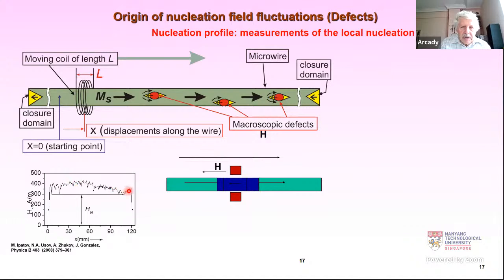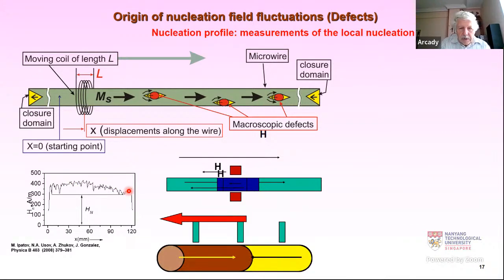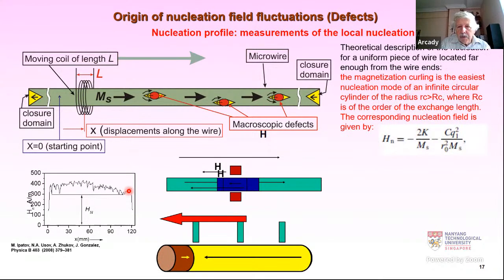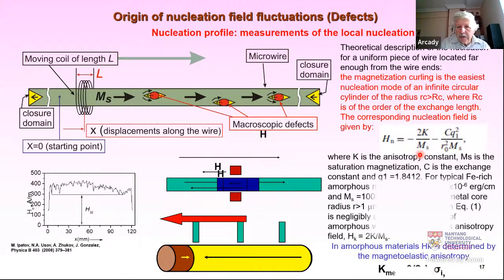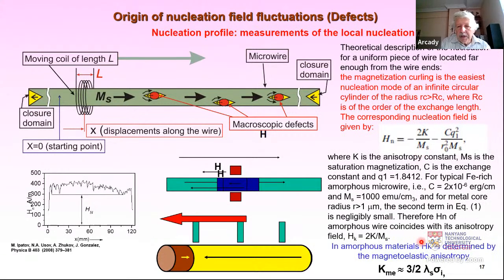And this fluctuation is because, when we nucleate a domain wall in the middle of the sample and propagate it, the nucleation field is closely related to the magnetic anisotropy, which in turn is affected by magnetoelastic energy. So the origin of these fluctuations is related to, for example, inhomogeneity of the glass, inhomogeneity of internal stresses, etc.